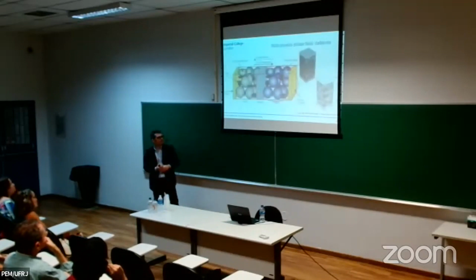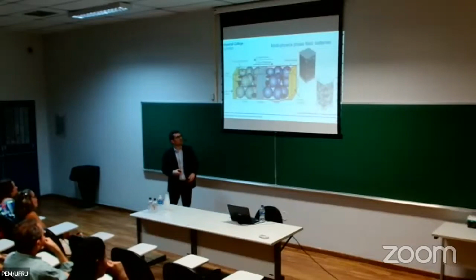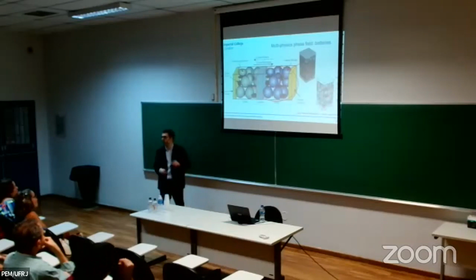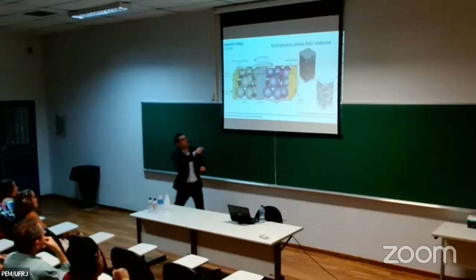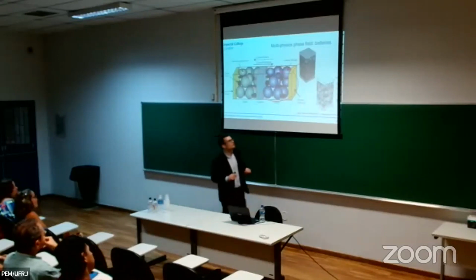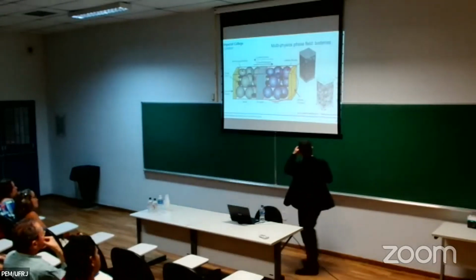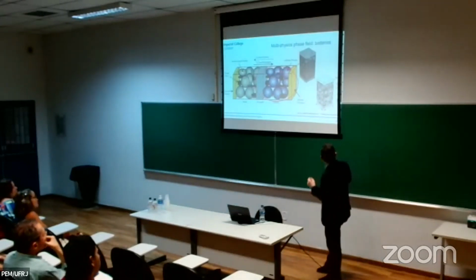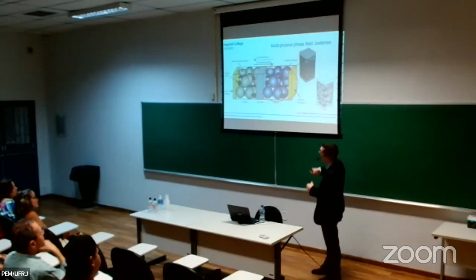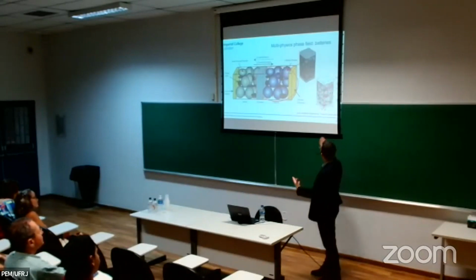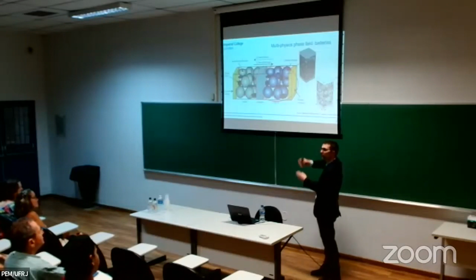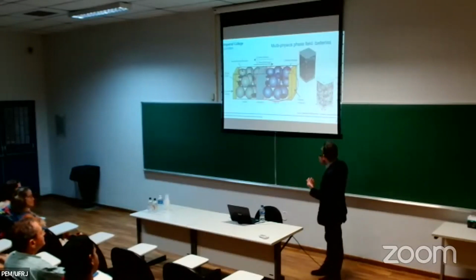But we've also taken this one step forward. This is together with colleagues at UCL. They have very advanced imaging facilities there, so they're able to characterize the full electrode, not looking anymore at one particle, but at the full electrode. And this allows us to look at the secondary phases, so not only the particles, but also the binder, the separator, and also the heterogeneity of the problem. For example, you can have electrodes with particles of different sizes, and we can play with the thickness of the electrode. So you take it one scale up.